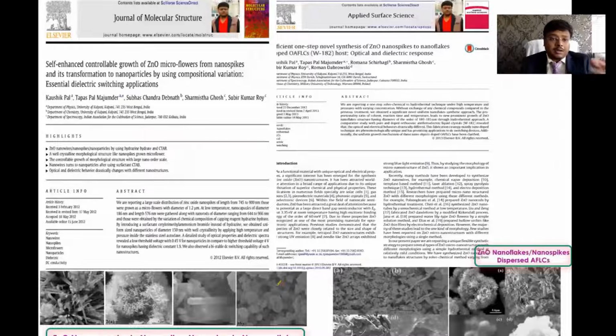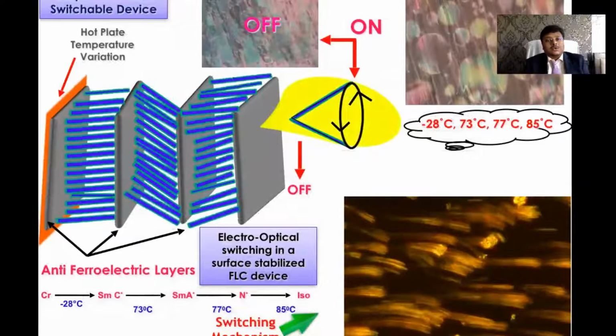So you can see the self-enhanced controllable growth dynamics of zinc oxide microflower structure to nanoparticle. This is how we can tune with the same procedure but a different material. You can chemically tune the morphology of several materials easily, so the optical, electrical, dielectric, and optoelectronic properties will all be changed drastically. Here I did the same thing, I just inserted zinc oxide with the liquid crystal. You can see the cavities, and inside there is a particle. This is kept by the liquid crystal molecules after annealing. And this is a novel switchable device.